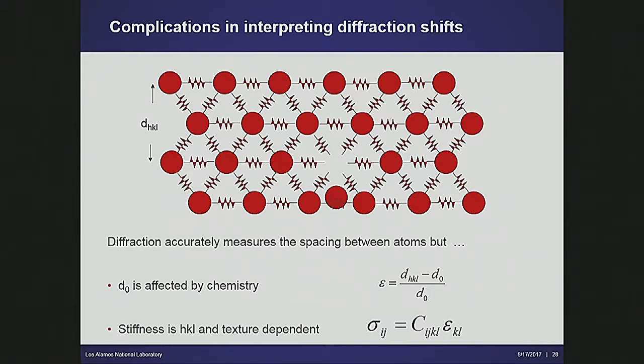D0 is affected by chemistry. The other thing that you may not have been paying much attention to yet is the fact that the stiffness is HKL and texture dependent, so that the stiffness between these grains for different lattice reflections is different in one direction than it is in another direction. And you have to understand that. And you have to understand how that stiffness varies both intrinsically in the crystal.